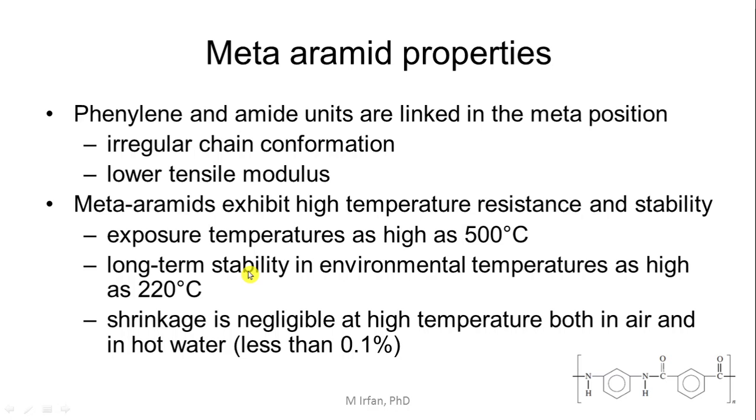That is, they can withstand working temperature of up to 220 degrees centigrade, whereas one-time exposure can be as high as 500 degrees centigrade. The shrinkage is negligible at high temperature, both in air and in hot water. It is reported to be less than 0.1%.